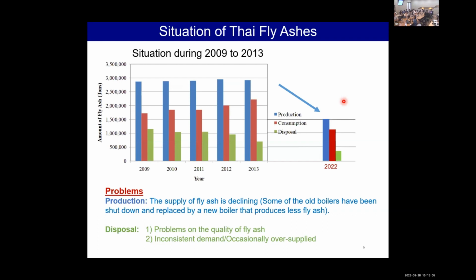Regarding the situation of fly ash right now, about 10 years ago fly ash was produced at about 3 million tons per year. Recently, last year, the production of fly ash was reduced. The reason is that some of the old boilers at the Mae Moh power plant have been shut down and replaced by new boilers that produce less fly ash. And there is still some fly ash that is disposed of because of problems with the quality of the fly ash, inconsistent demand, and occasional oversupply.